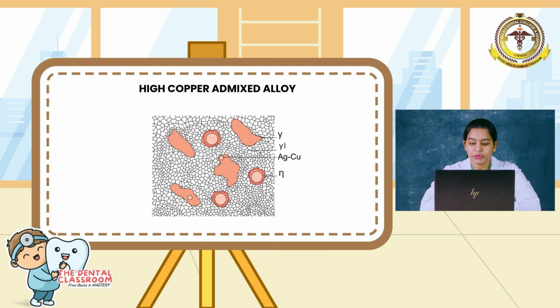The microstructure of set high copper admixed amalgam consists of core particles of unreacted gamma phase and unreacted silver copper eutectic, which is surrounded by a halo of eta phase embedded in the matrix of gamma 1 phase. Here the gamma 2 phase is eliminated and replaced by a stronger eta phase.